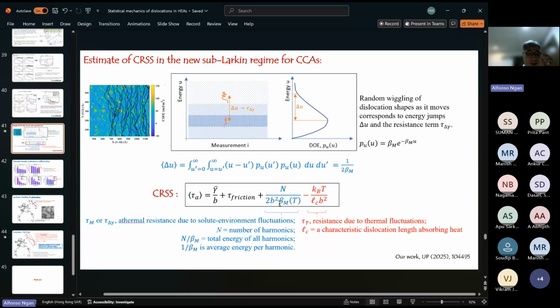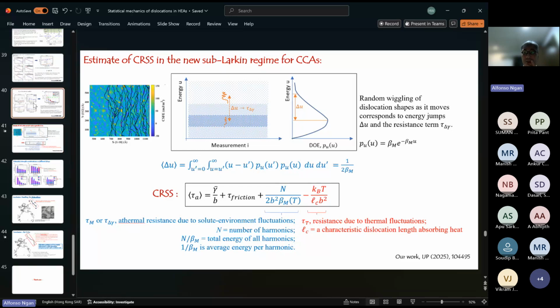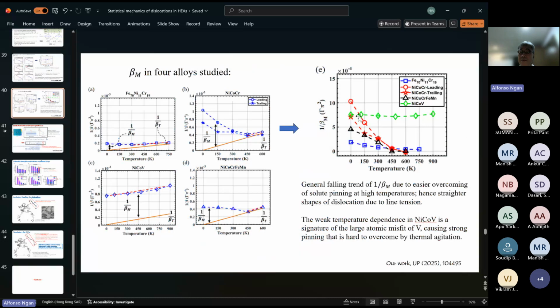And in fact, we can see that from the composite. This green data would be from nickel, cobalt, vanadium, which should be compared with nickel, cobalt, chromium. They are isostructural. Both of them are FCC. The only difference is you have chromium in one case and vanadium in another case. So the chromium would be the red circles. It drops very rapidly, while the vanadium stays strong.